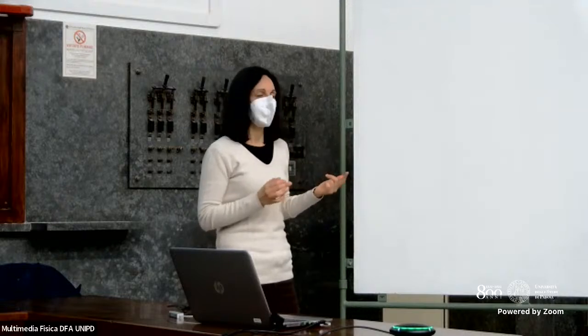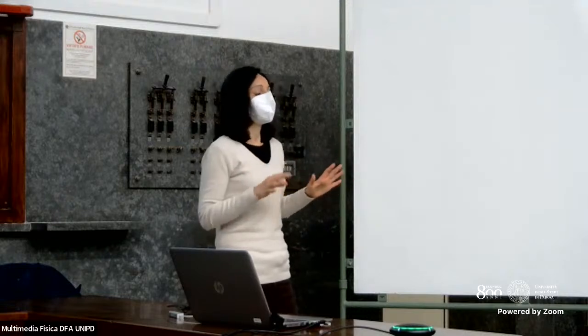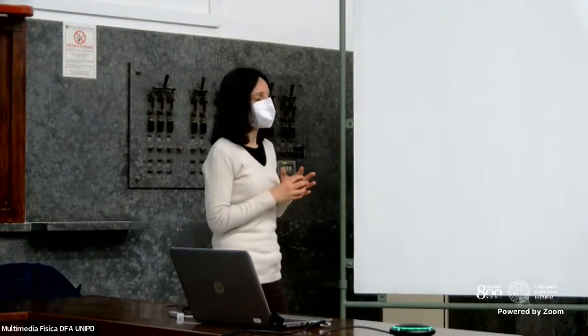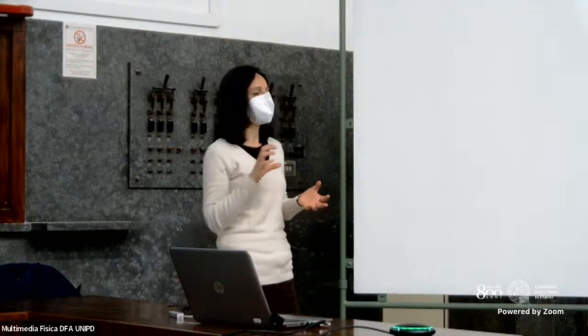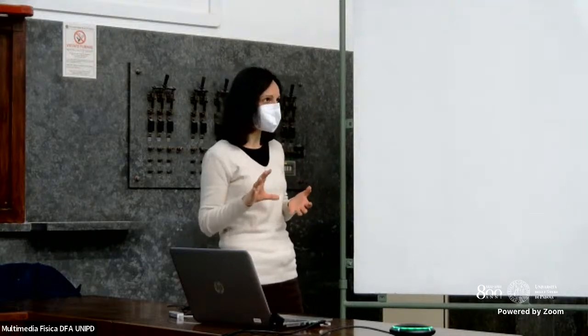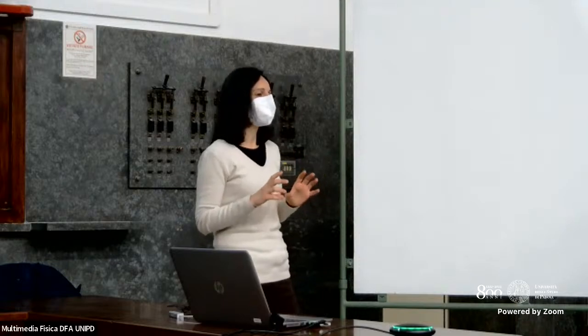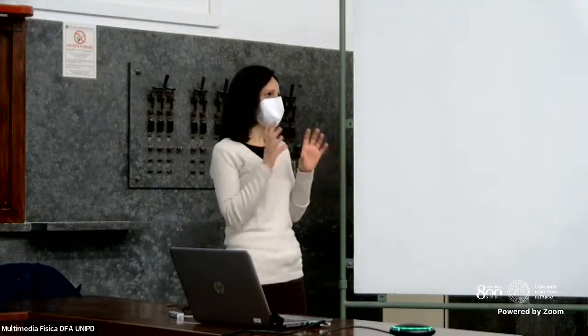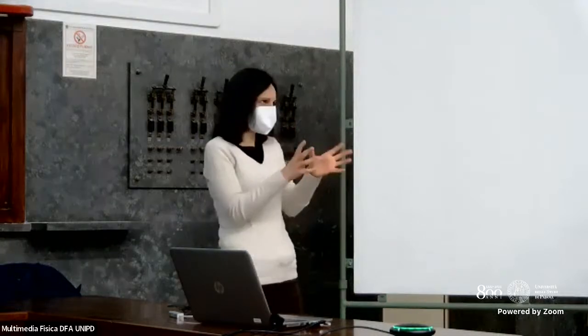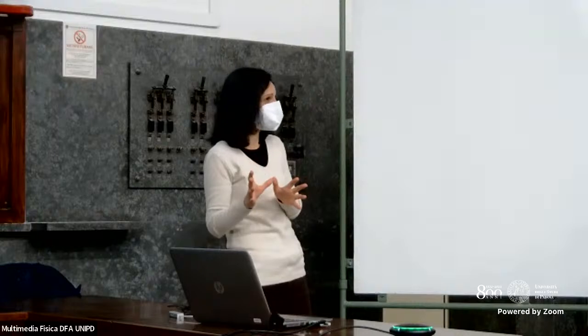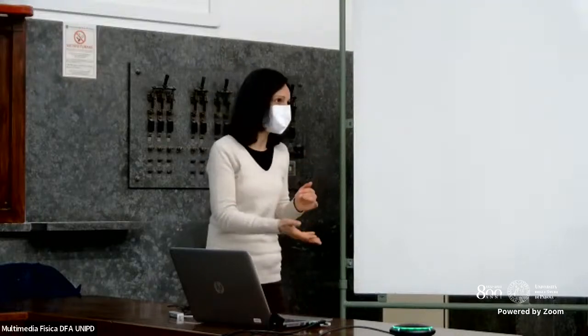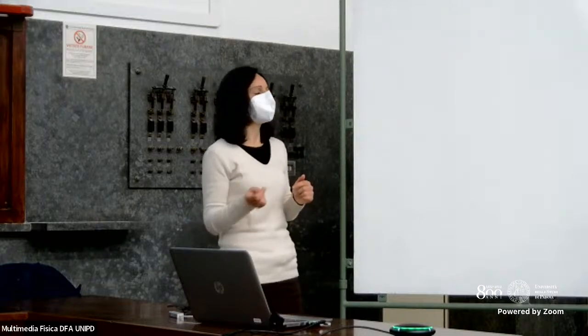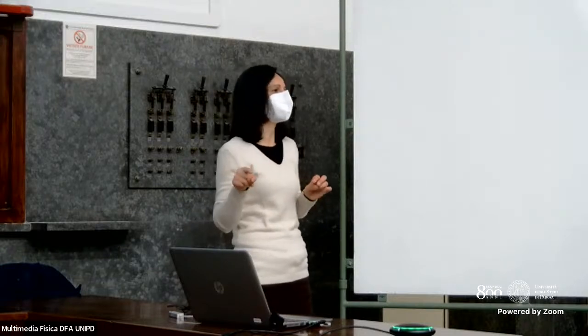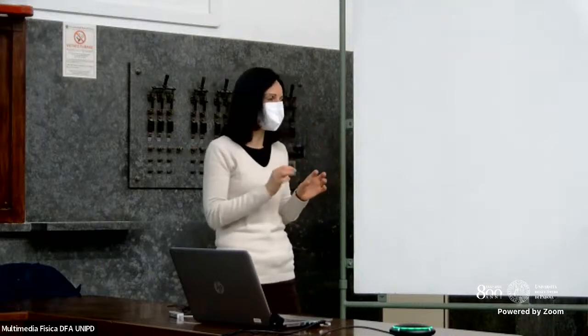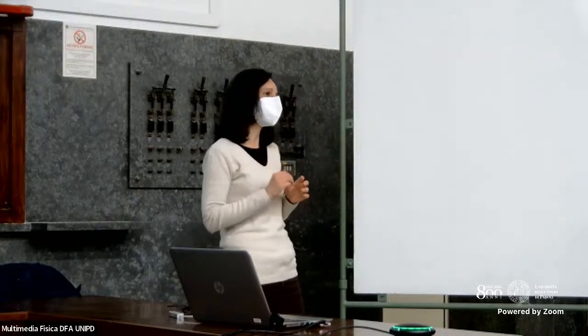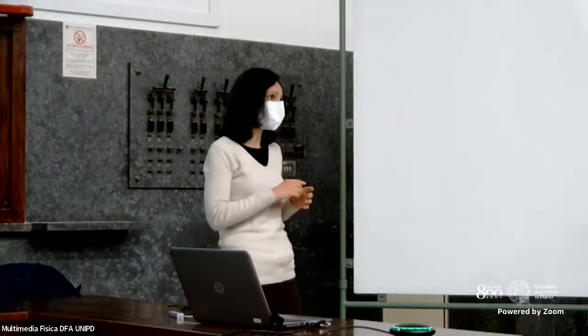Regarding SU8, it was really complicated. Usually, to be successful in electrospinning, you need to use a highly viscous solution. In this case, we could not use the bare SU8 resin, but we added some solvent which enables faster evaporation of the materials. In particular, all the pictures that I showed you with the different beads or fibers with different sizes were obtained by using different amounts of solvent embedded in the starting solution.